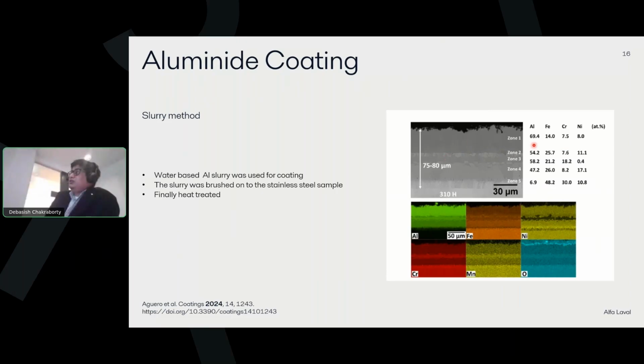And as you could see, as you go down, the concentration of aluminium goes down. And this could be a good way to protect the stainless steel, because when this is exposed to air, you form this alumina layer.